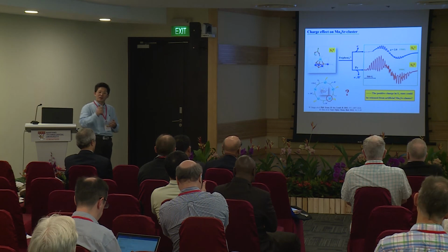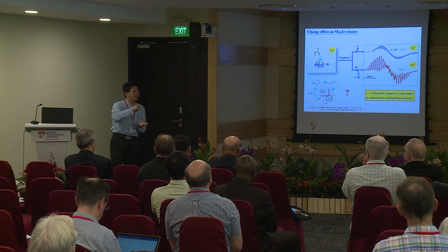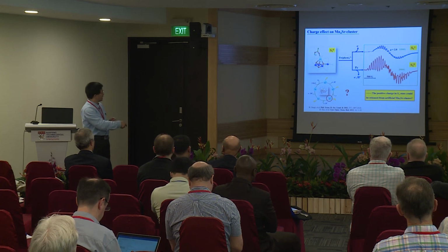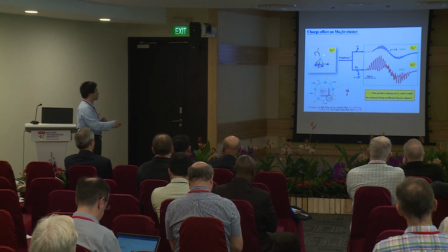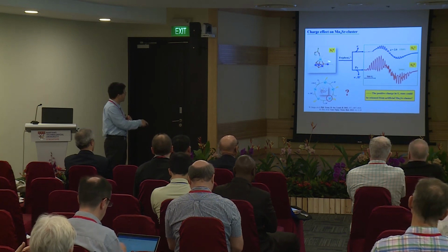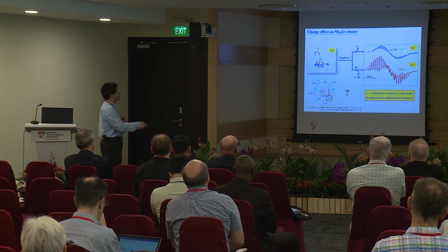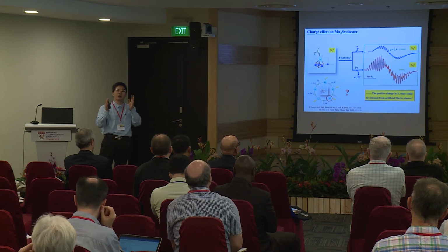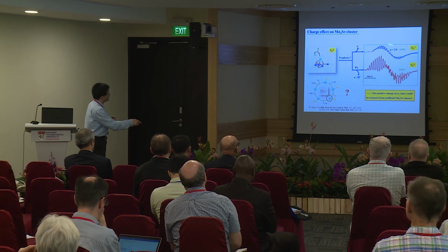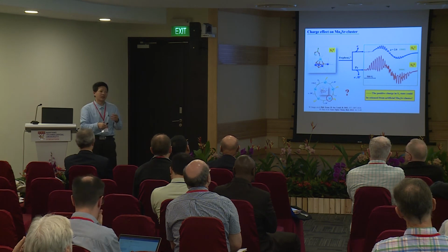Another thing: this morning I asked Holger about the proton release and the electron release. Probably we can handle these things by using the model complex. Here, the 4 manganese, 1 strontium, the whole cluster charge is 0. There's no charge. It's one state. But when we take one electron out, we see immediately this signal. And it is narrow, 1,500 Gauss wide. But when we take the proton, you can see the signal. After that, we add pyridine as a base to take the charge away.